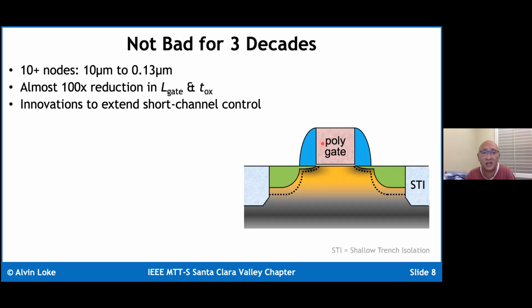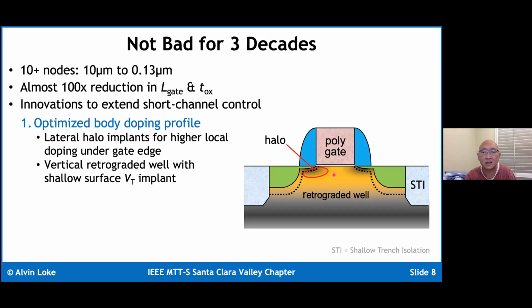There has been several key innovations to extend short channel control. The notable one is that the channel profile in the transistor, both horizontally and vertically, is non-uniform. Okay, and so the textbooks where we basically see uniformly doped bodies, that's obviously a big lie. Generally what you do is you have to optimize the body doping profile by using these lateral halo implants that are high tilt, high angle implants that get just underneath the edge of the device here. And the idea is that you want to basically increase the doping concentration to make the depletion regions thinner so that you can recover some short channel control.